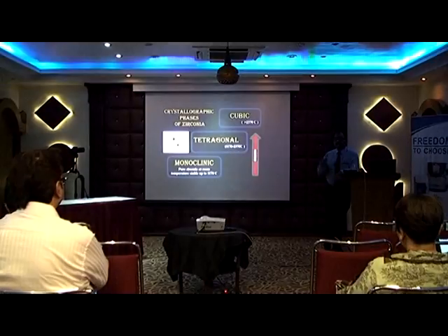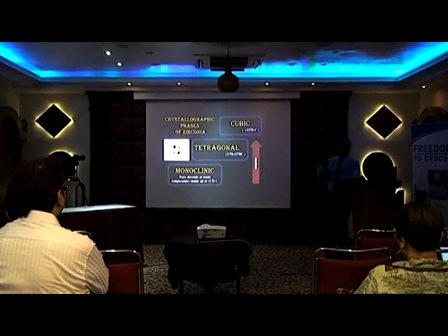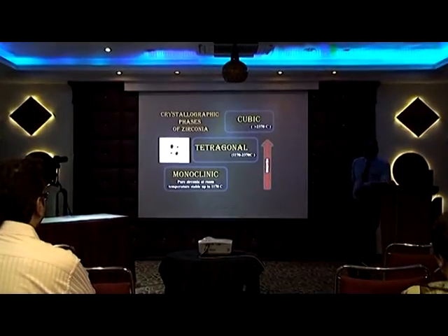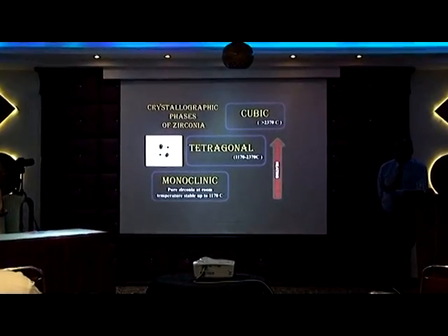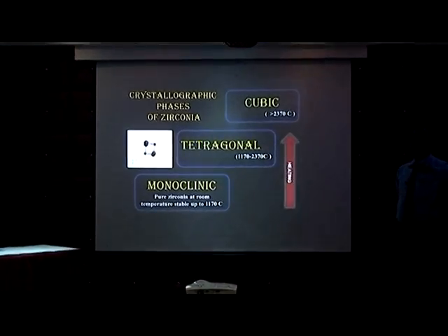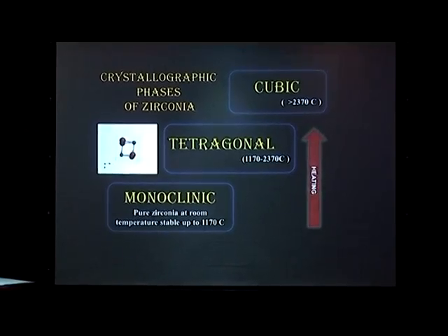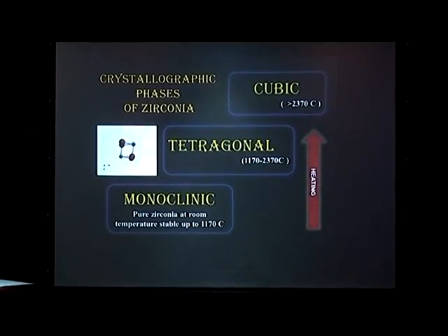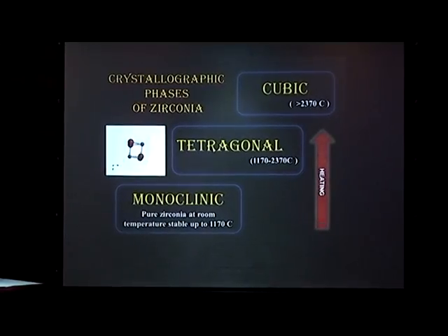But if you do not send it for reglaze, then I would advise that kindly please keep a polishing burr, silicone burr, and polish that area. Then you will get back, as per the literature, and even the studies that we've done, 50% of the strength. That's hell of a lot. But at the same time, if you've removed enamel, you remove dentine from the veneered surface, and the substructure of zirconia is there, which you will identify by sparking, please do not grind more.